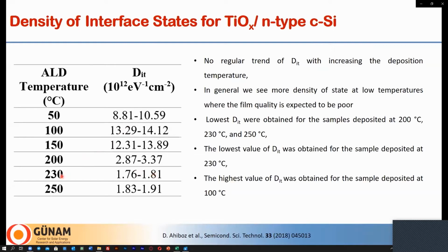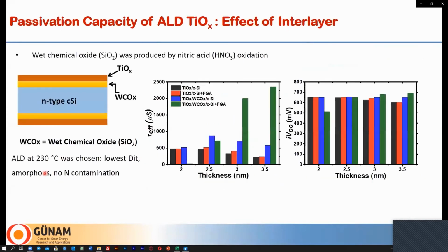Indeed, we used only this film, and we studied the passivation quality of ALD grown titanium dioxide at this temperature. We used a very thin wet chemical oxide, about 1.4 nanometer, between titanium dioxide and silicon, and we put titanium dioxide on both sides of an N-type wafer. You see here the carrier lifetime as a function of thickness of titanium dioxide, and here we compare two conditions: one with chemical oxide, and the other without chemical oxide, where titanium dioxide is directly deposited on the N-type wafer. In both scenarios we used forming gas annealing.